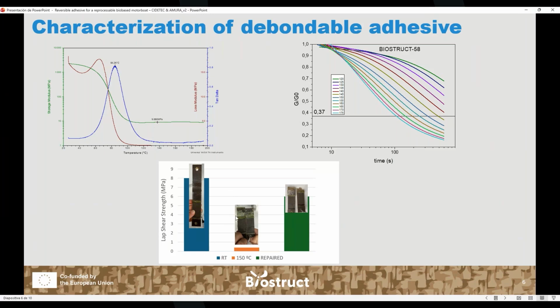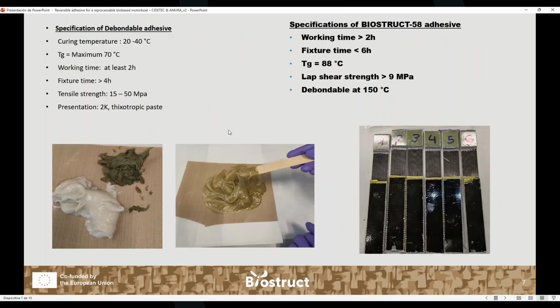And in order to demonstrate that we can also rebond these parts, we applied heat and pressure to this specimen, and then we tested again. And we obtained a lap shear strength of around 6 megapascals, which means that we recovered more than 75% of the initial properties. So here you have a summary regarding the specifications that we fixed at the beginning of the project regarding the curing temperature, TG, and so on.